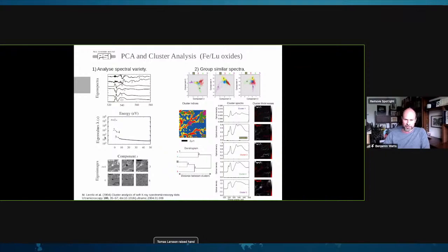And we can see that the eigenvalues associated with these drop in magnitude quite quickly. And from the images, you can see that they really go towards noise at the end. So we can see here in the spectra and the images, the initial components show structure that looks real, and then the later components just show noise. And it's up to a human to decide where that cutoff is, because there's no algorithm that can really do that efficiently. So once we've done that, we have a way to understand the variety, but it doesn't tell us